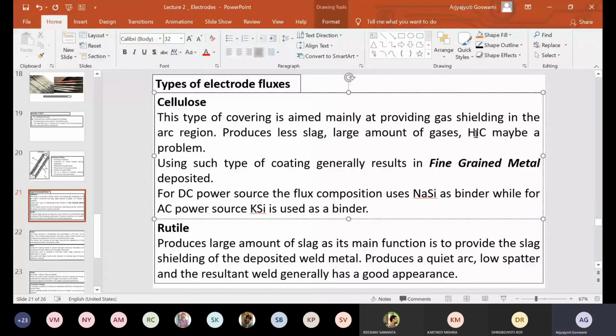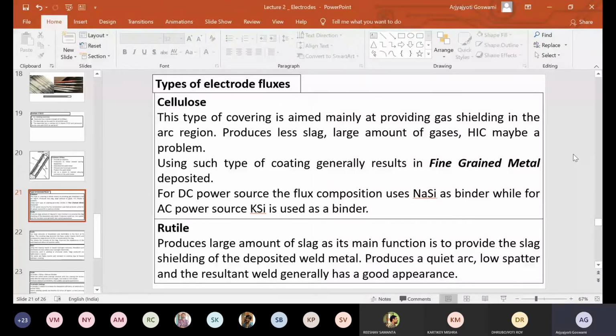Hydrogen induced cracking may be a problem in case of cellulosic coating. Because cellulose will prevent any atmospheric contamination, but whatever is there inside the weld metal, that may be a problem. Of course, nowadays it is not that much of an issue, but still cellulosic coating can give very proper shielding, but it will be a very fine grained material, and since cooling is very fast, the inclusions, whatever inclusions are there, won't get time to move out. So the inclusions may be a problem, which may lead to HIC, which is hydrogen induced cracking.